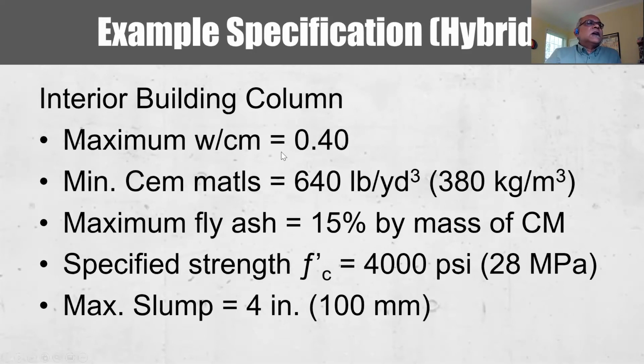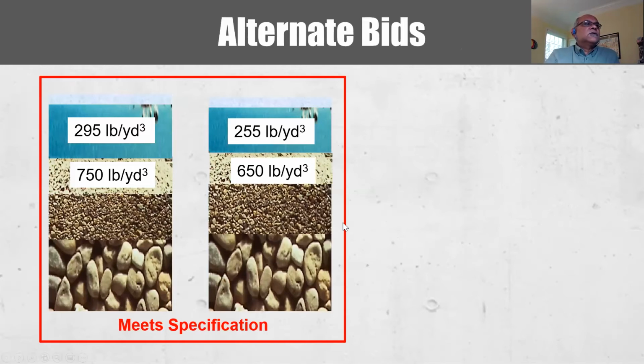So I'll just use this example to demonstrate that you can get considerably different mixtures from two different producers. One producer may start off with the required mixing water to get that slump, and based on the water cement ratio, his cementitious content goes up to 750. Another one will choose to use a more efficient admixture system, and therefore optimize the mix a little bit by reducing the cement content. And when we look at this, we talk about the water and the cement portion of the concrete mixture as the paste volume, and we want to minimize the paste to improve performance.